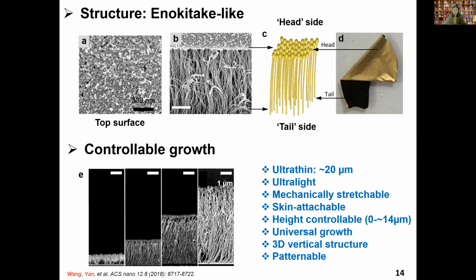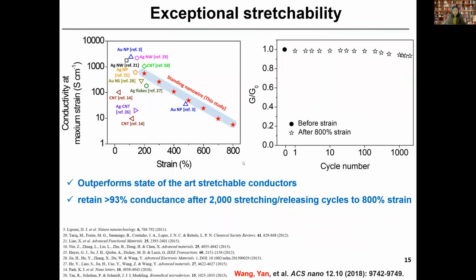This film is fabricated by a wholly solution-processed method. The length of the nanowires can be tuned, ranging from a few hundred nanometers to 14 micrometers. When we directly grow the film on silicone rubber, the film can be stretched to 800% strain without failure.